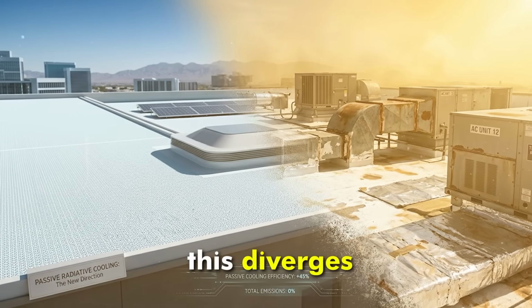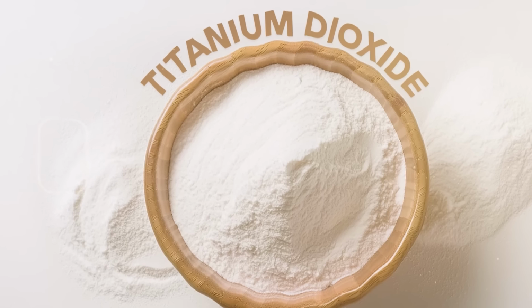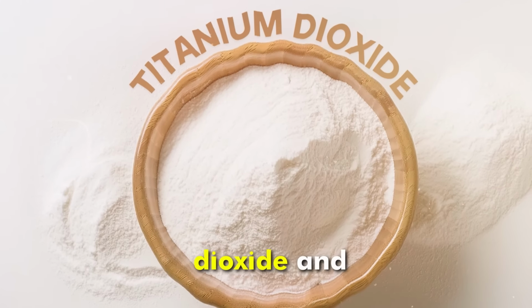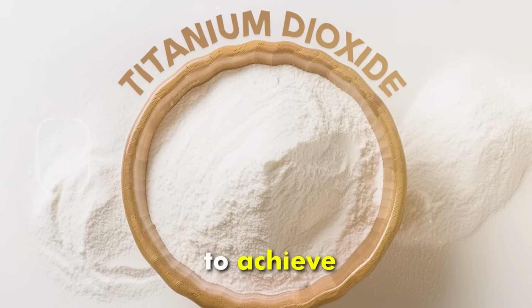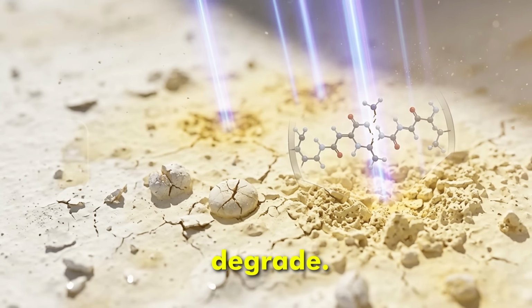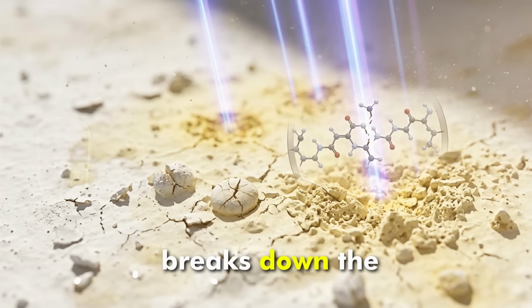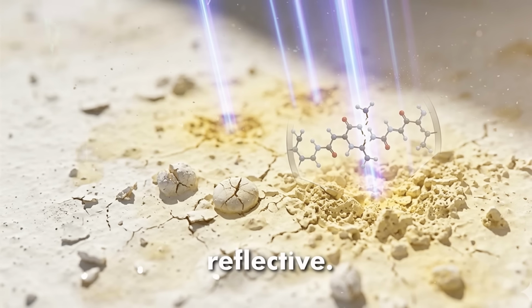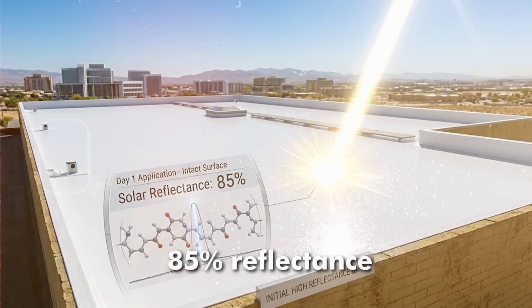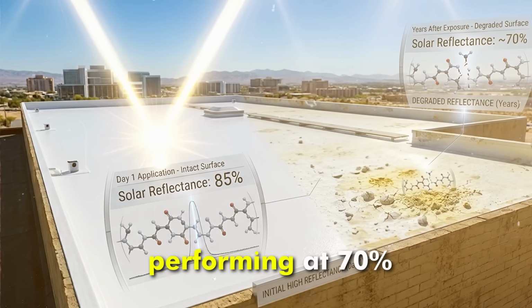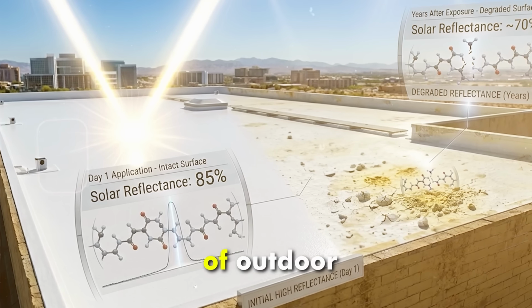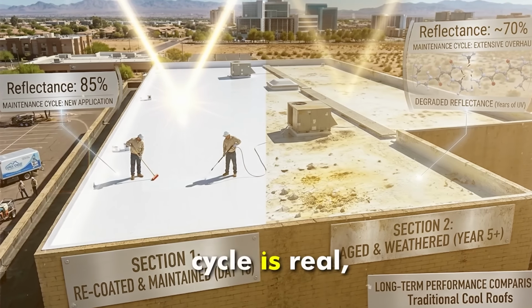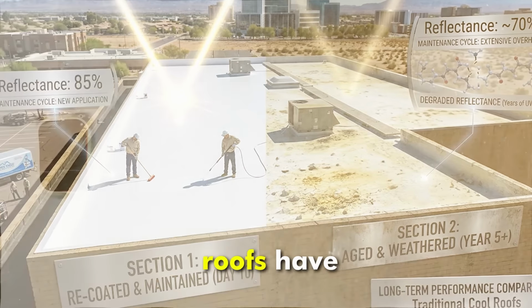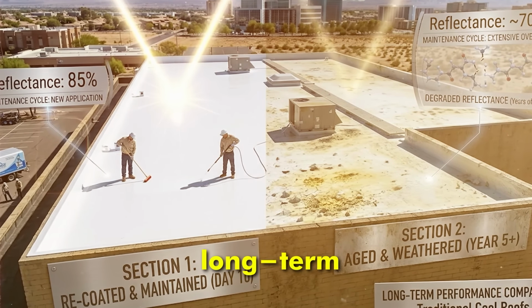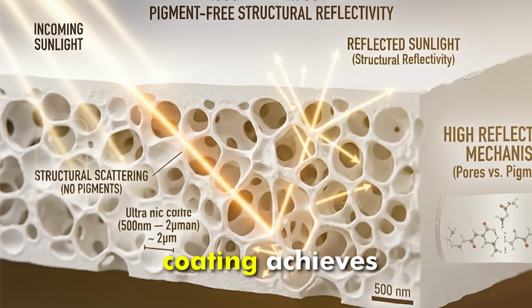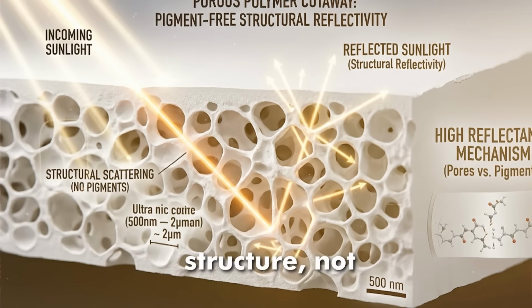Now, here is where this diverges from everything that has come before it. Traditional cool roof pigments rely on titanium dioxide, and similar compounds to achieve reflectivity. Those compounds degrade. UV radiation slowly breaks down the chemical bonds that make them reflective. A white coating that performs at 85% reflectance on day 1 may be performing at 70% after a few years of outdoor exposure. The maintenance cycle is real, and it's one of the reasons cool roofs have underperformed their theoretical promise in long-term deployments. The porous polymer coating achieves its reflectivity through internal structure, not pigment.